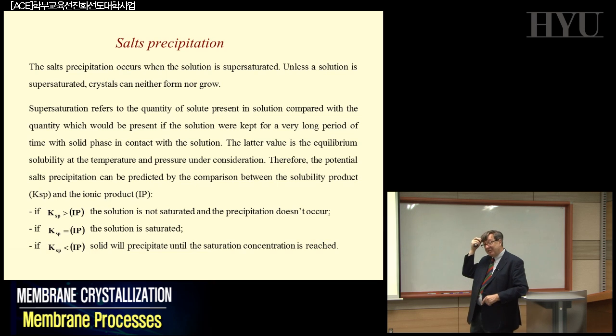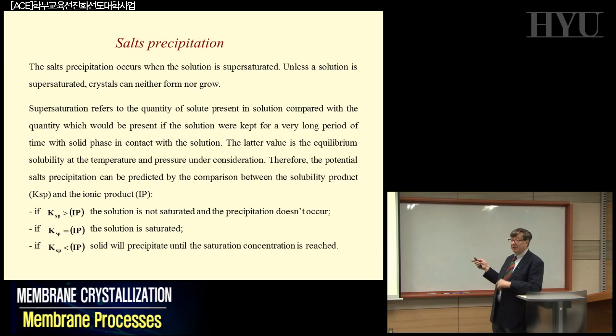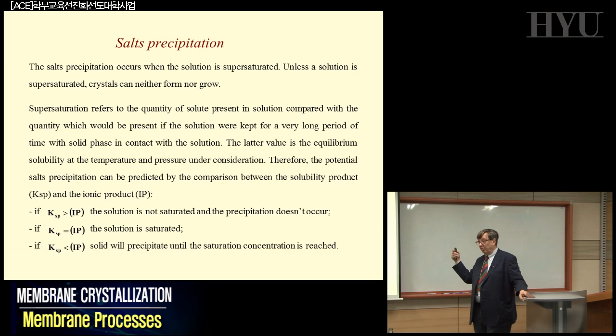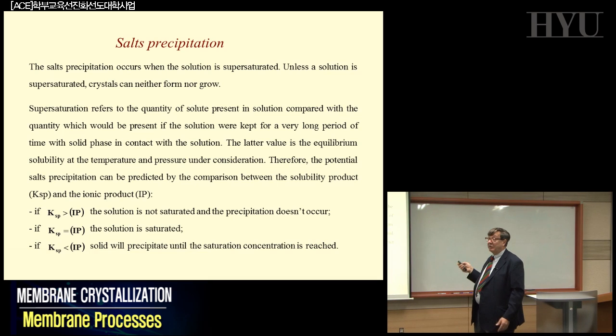So you can produce a crystallizer, which is one of my hairs as hollow fibers, the one that Soo-Kyung will produce on the 10th floor, a single fiber, a small piece, that is a crystallizer when you make the right assembly. Because you don't have too much material available, you just have a very small membrane surface, but it's useful. In seawater or similar, not so easy. You need a huge plant. And you don't have water and paracetamol or water and trypsin. You have hundreds of different compounds.